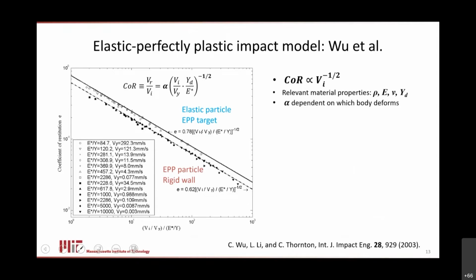Well, the first thing you can do with these data is analyze them quantitatively and try to extract some information about plasticity. For this purpose, we found it useful to use a model developed by Wu et al. in 2003. This is a really nice, very simple model that I think captures the essential physics while ignoring a lot of the details. This model is based on a whole bunch of finite element analysis that Wu did of a whole bunch of different material properties impacting, and it's again a matched material impact situation. But what they're modeling is not the full complex problem that could occur. They're not including work hardening, rate hardening, adiabatic heating and softening. A whole bunch of details are subsumed into a single effective yield stress for an elastic, perfectly plastic impact. So this is a baseline plasticity model.